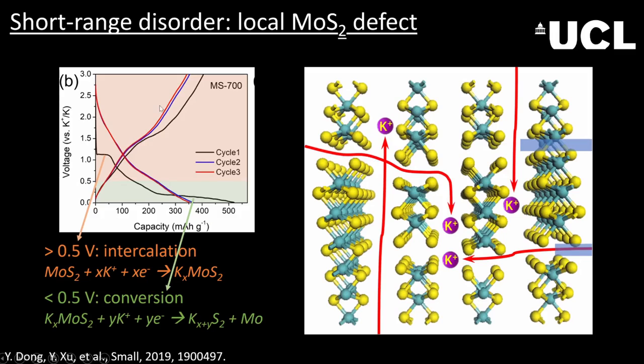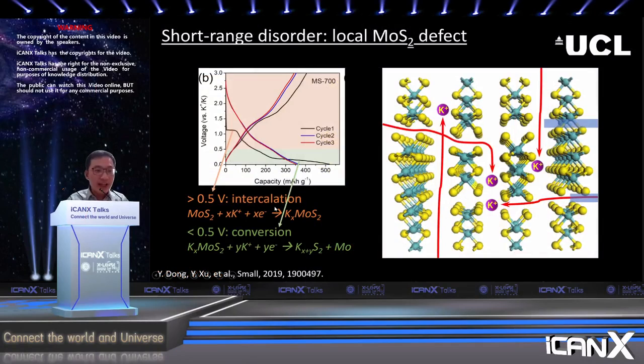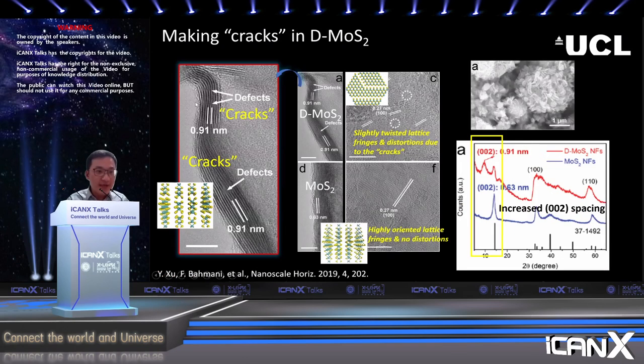Using HRTEM, we are able to see there are cracks in each layer, so that if you look at it from the side of the material, the layers are not continuous, they are discontinued by the cracks. We also synthesized the control sample where there are fewer defects in the material. So we can see from the side that each layer is a lot more continuous compared to the defective molybdenum sulfide.